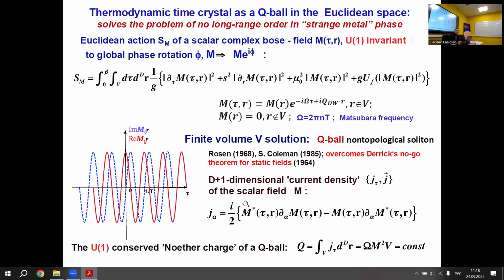This is the d plus one dimensional current density. So we take now alpha equals time, and then it is the Matsubara time derivative. And when you substitute this expression into this formula, you will get this expression. What does it mean? Here is omega, this is the Matsubara omega standing here, the rotation frequency in Matsubara time. M squared is the square of the amplitude of the local deformation. This could be either spin wave or phonon field. V is the finite volume of the QBall. So outside this volume, M equals zero. And this is a strict result.